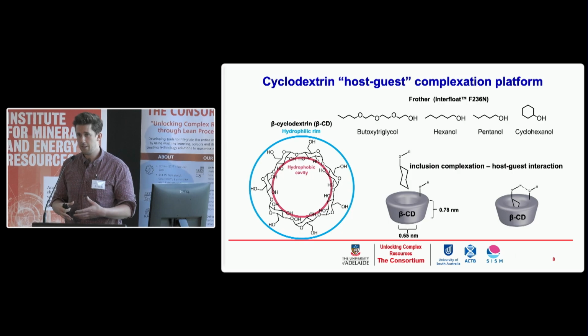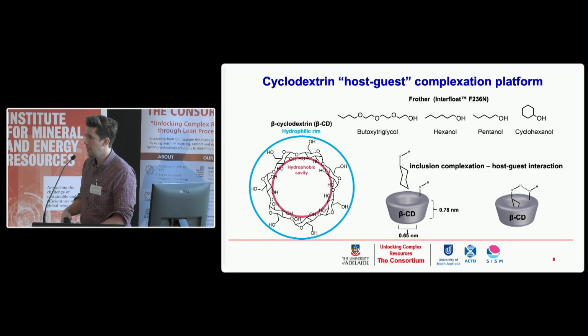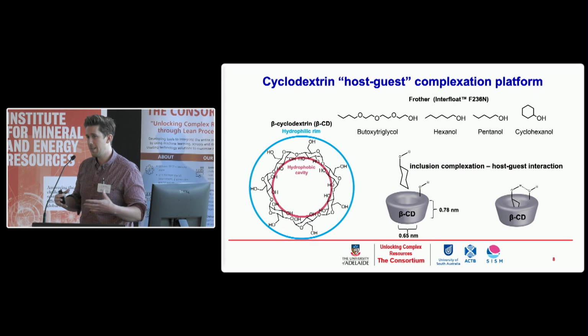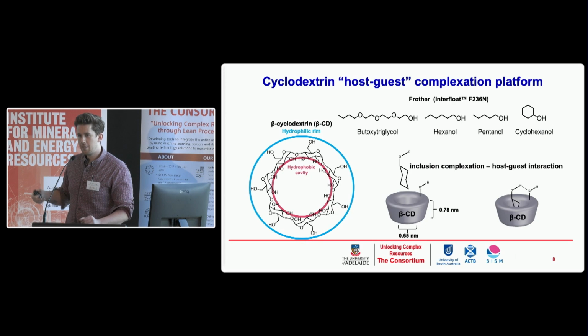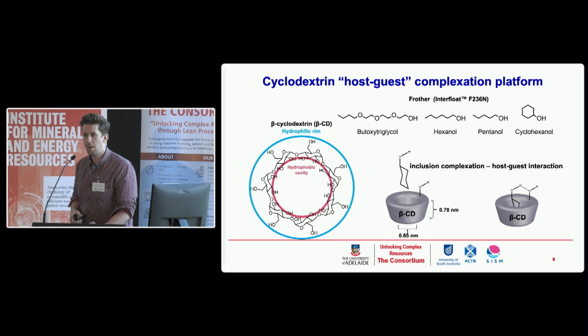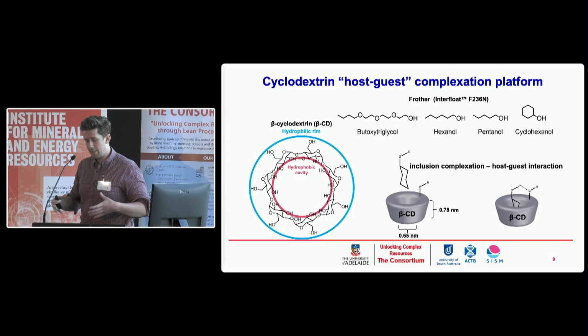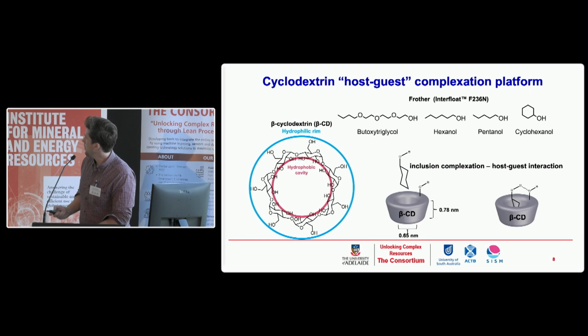Cyclodextrins have different sizes depending on how many sugars are in their ring. Beta-cyclodextrin was selected as we believed it had a good size complementarity to cyclohexanol, and we were kind of hoping that we might get some degree of selectivity for that component just based on that steric bulk. We didn't really achieve that, but that's life.